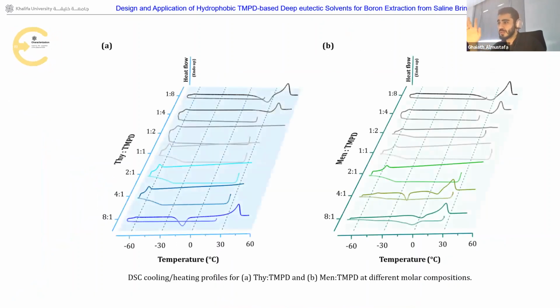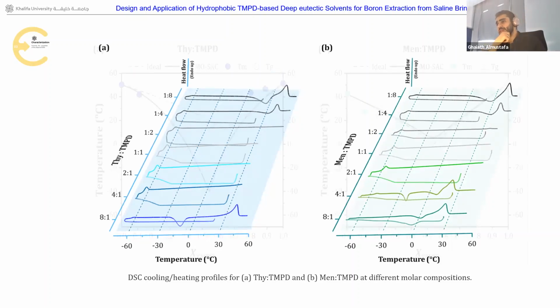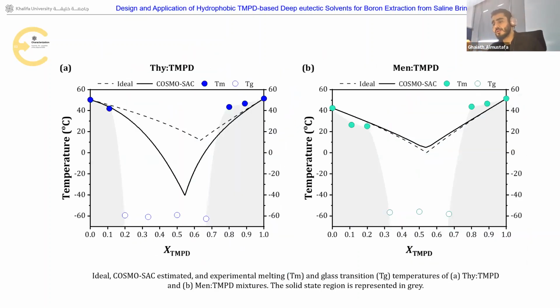As for the characterization, it is very essential to study the phase behavior and the thermal stabilities of these solvents, and we do that using DSC. As you can see right away, compared with the two components, the menthol system and the thymol system, they both, from the ratio of 2:1 up to 1:2, have a very depressed melting point. And in fact, we could not detect a melting point.